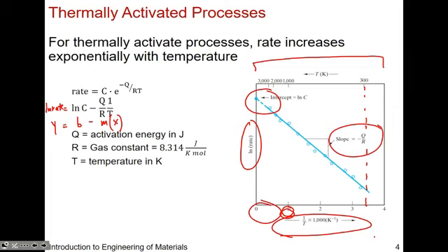You have to be careful that in this linear regime, what you're looking at is actually one mechanism. So if an ion is diffusing along or something's being activated, vacancy hopping, atoms hopping, what have you, that's one type of process. When you get to really high temperature and really low 1 over T, you have to be careful that you're still in the same regime.